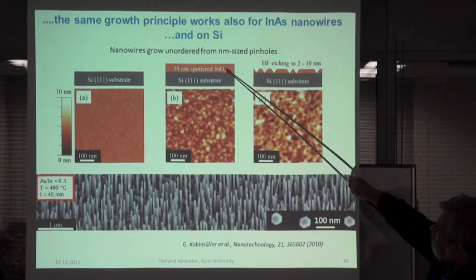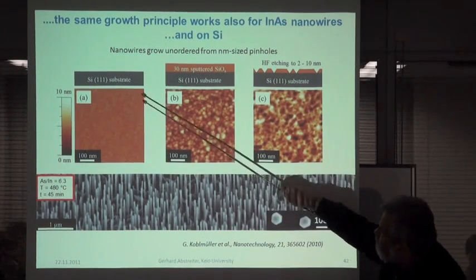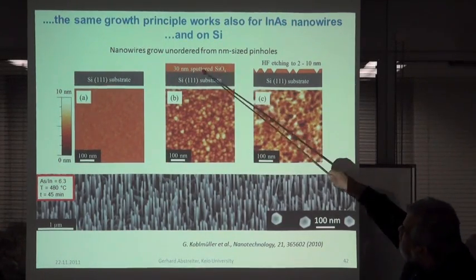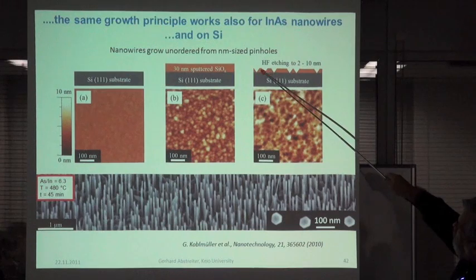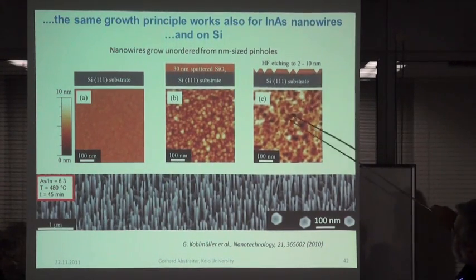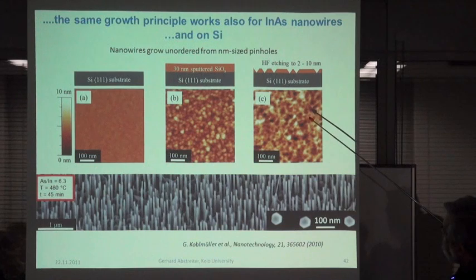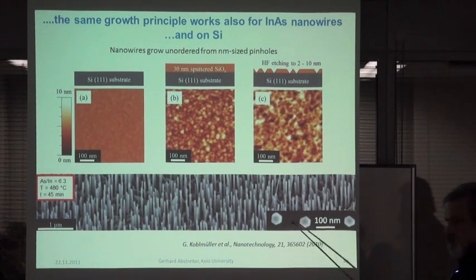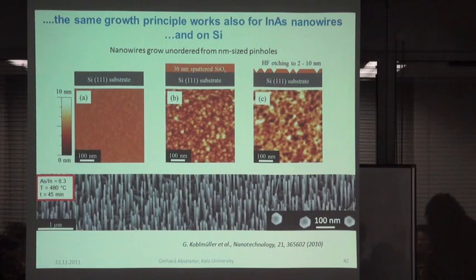So what we do is, now this is a bare surface with natural oxides, then we sputter, then we do an HF etching and get these pinholes in the system, and in these pinholes we then get the growth of these nanowires, and also they have this same shape. So this is just on silicon random growth.